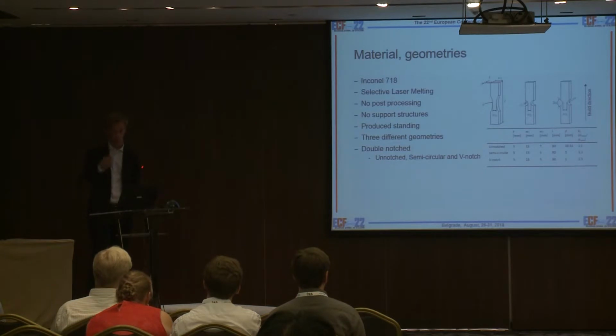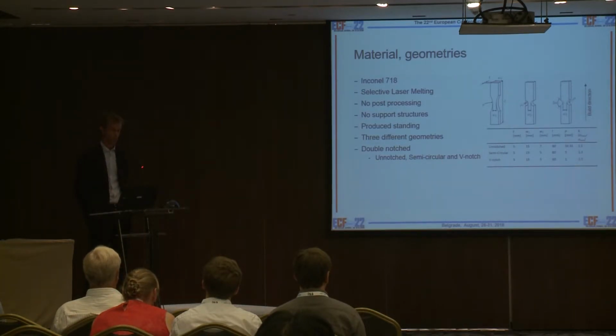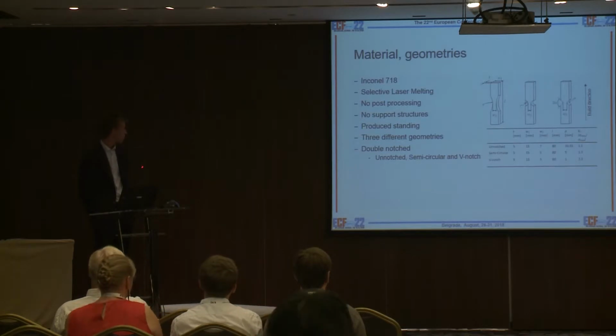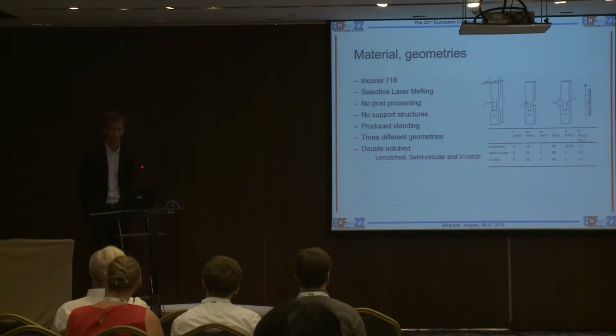I've been working on notched specimens to see the effect of both building angle and the stress intensities. I've been working on Inconel, produced by selective laser melting. No post-processing has been done to these specimens. So there are no heat treatments, no machining, nothing. This is just the as-built state. And also there have been no support structures, as you would normally have to get a good material quality. So we see the effect of not using support structures. They have been built in the set direction, standing, and there are 3 different geometries: one which is unnotched, a semicircular one, and a V-notch.